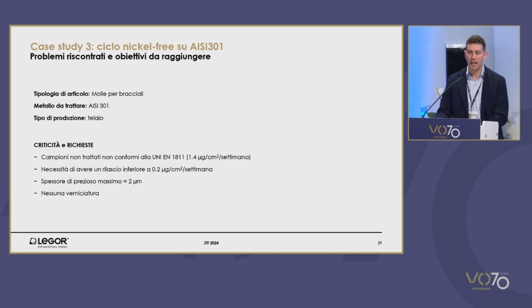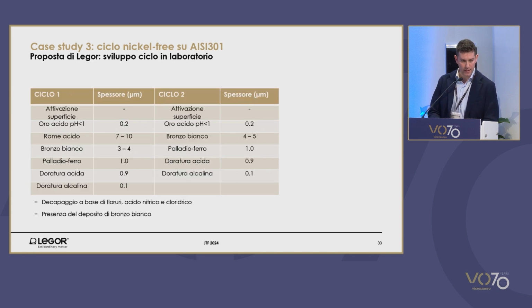The client requested a 0.2, despite the regulation being more tolerant. And the precious metal shouldn't be bigger than 2 microns and shouldn't require any painting. 2 cycles have been tested in the lab. The activation of the surface was similar to the ones that we've seen earlier on, and the adhesion was promoted with the acidic gold plating.